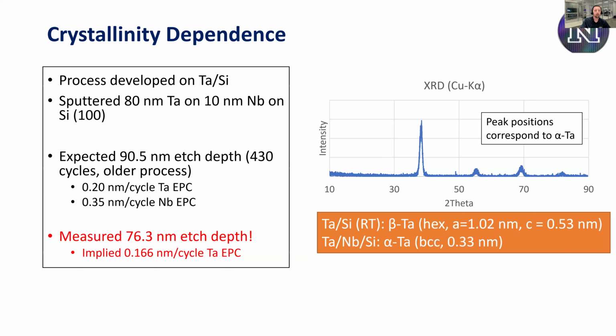We weren't sure the ALE was going to show it, but, surprising to us, we actually saw a difference in the etch per cycle. We saw a decreased etch per cycle when we had the alpha phase tantalum, and that was verified in XRD that it was in fact alpha phase. So we thought this was pretty interesting, that this ALE process seems to be sensitive to the metal film crystal structure.